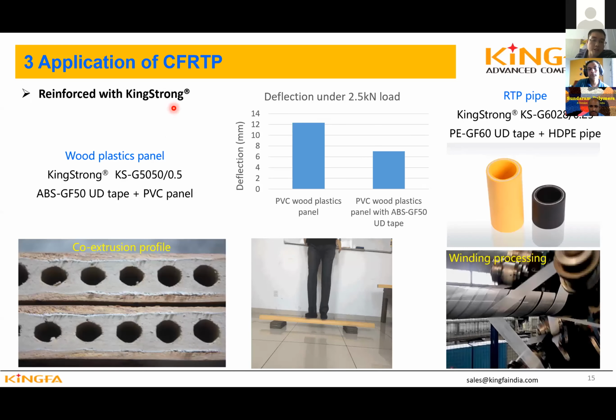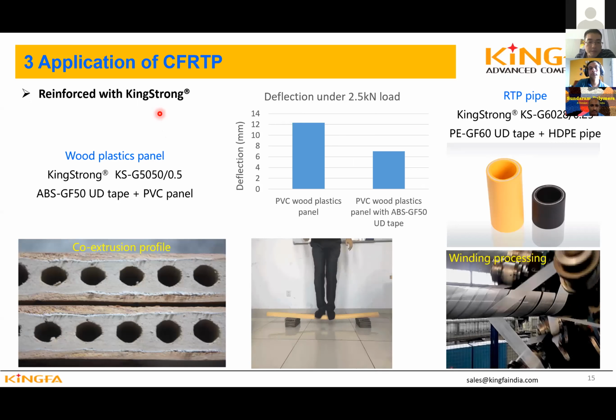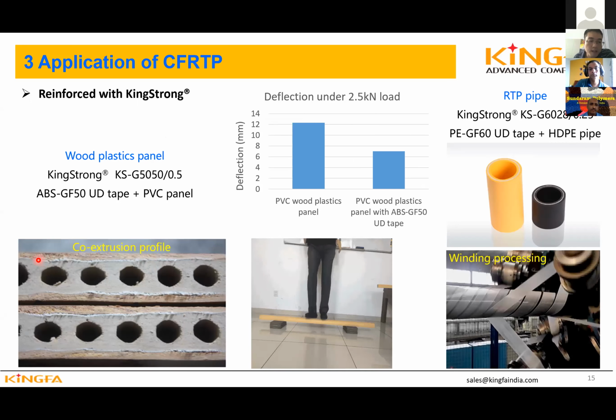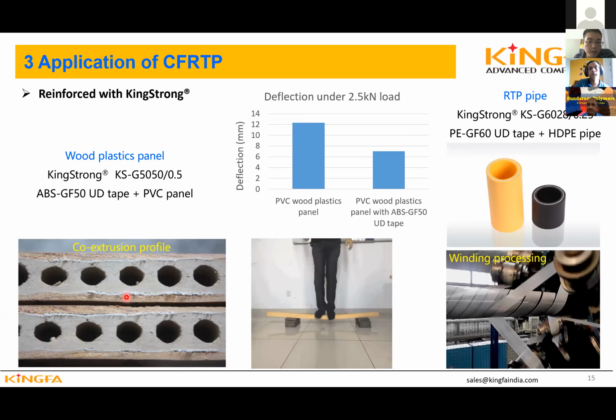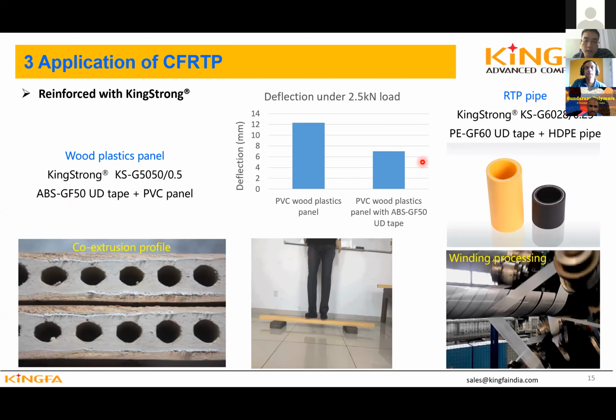Here are some applications for the UD tape. In this photo, this is one PVC panel. This is wood plastic. And in the middle layer, we have 2 layers of UD tape. This is ABS with 50% glass fiber. After we add these 2 layers in this profile, the deflection under this load is decreased a lot. This is a video, some person standing on this to check whether it will break or not. So its performance is very good.